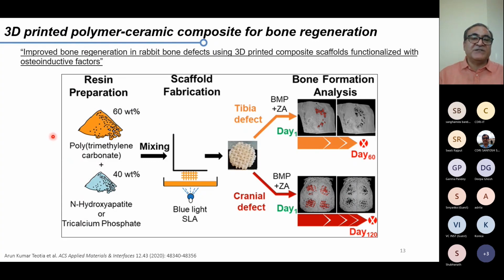It was a very tedious job, but we developed a resin which is PTMC, polytrimethylene carbonate, which is 60%, and it also has a photo cross-linker put on that resin. You can get this synthetically, you can get it commercially available, but then you have to put a photo-initiator here, actually coupling on that.